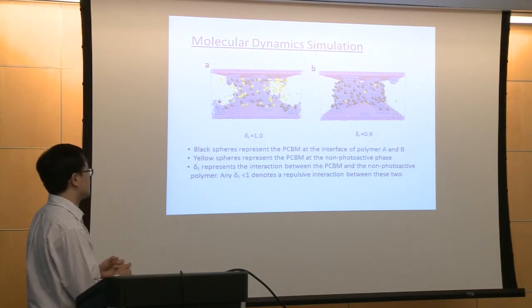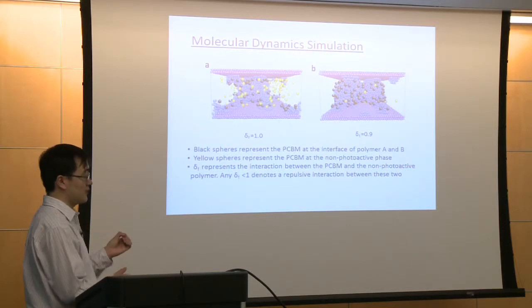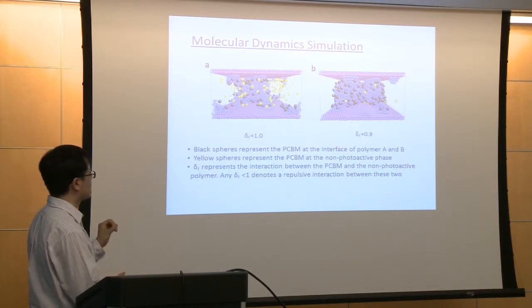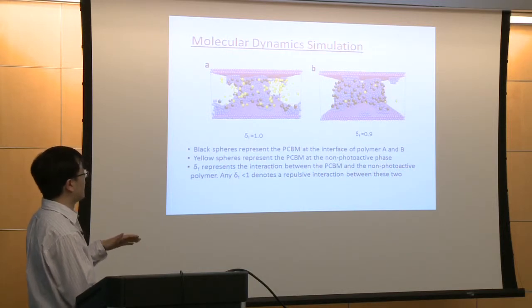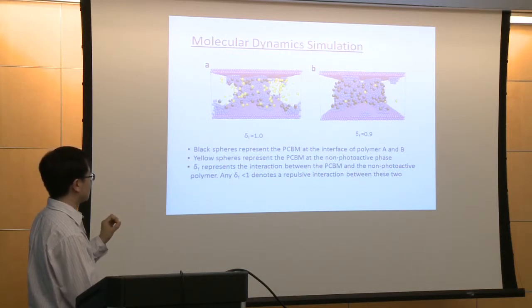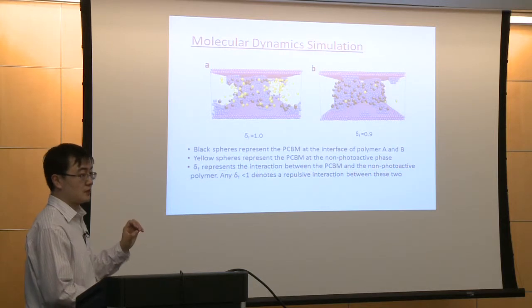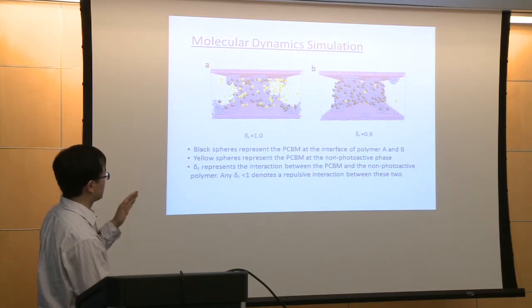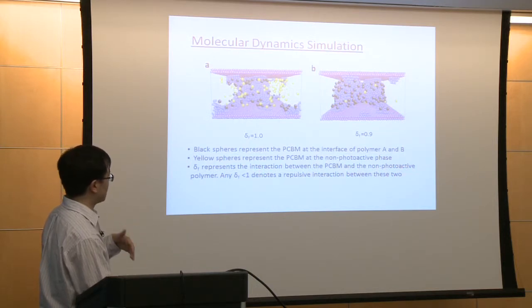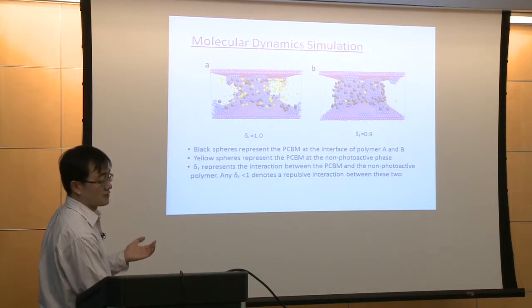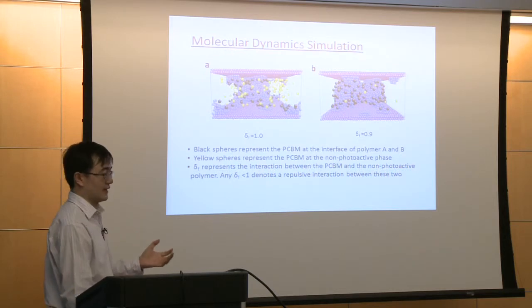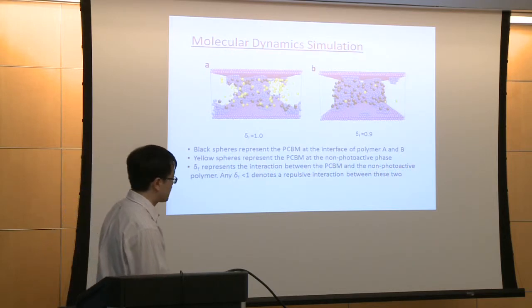However, if we change the value a little bit, which means there's a very little repulsive interaction between the PCBM and the other polymer, you can see a significant difference: most of the PCBM will go to the interface between the P3HT and the other polymer. So these are the results from the theoretical simulation, and the results give us the confidence to continue our experiment.